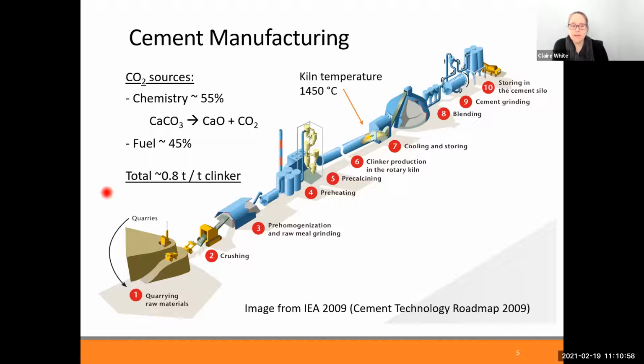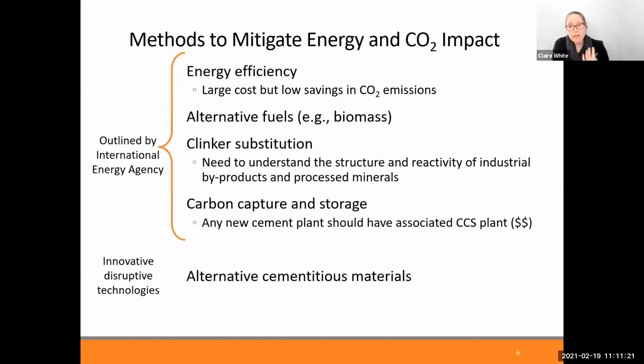And then if you look at the amount of CO2 per ton of clinker that comes out of the kiln, you're about 800 kilograms of CO2 per ton of clinker. And so this is all based on the fact that limestone needs to be decomposed. So you get oxides that react with the other elements in the system, and also needing to get to high temperatures. So there's a lot of people working around the world on how to reduce CO2 emissions associated with this industry. And so there's 4 main areas that have been talked about, including by the International Energy Agency. There's the energy efficiency of the kiln. So can you mitigate waste heat from being lost? Alternative fuels, so biomass as an example.